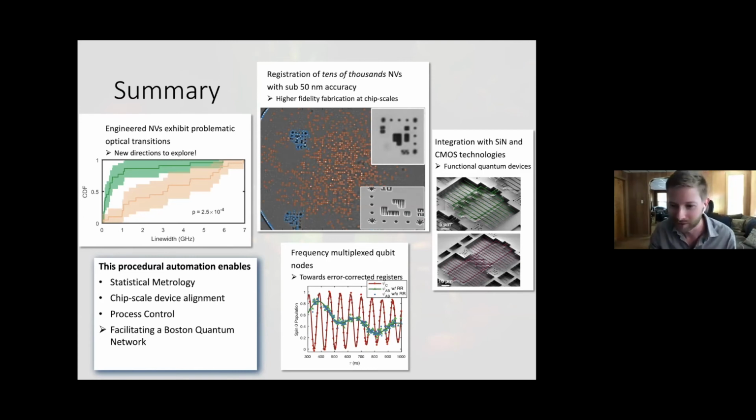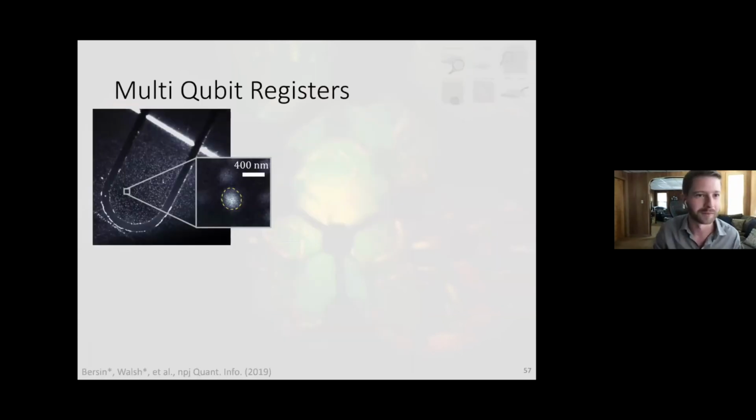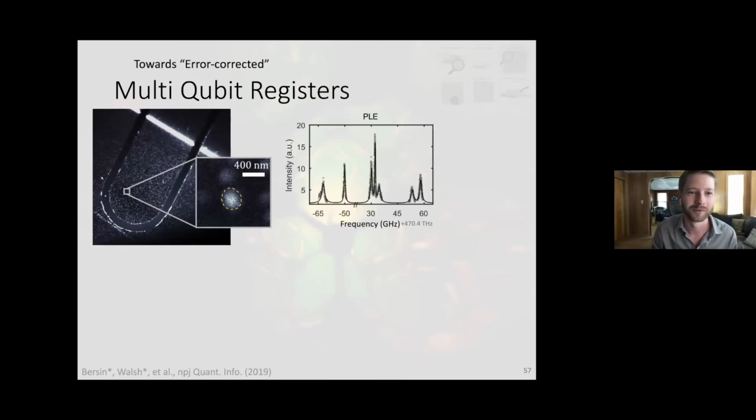And so let me just see if I have a backup slide here. Actually, right here is exactly what I'm talking about. In this particular node, we programmed the microscope to, instead of just going to find all of the sites there are, specifically look for a certain type of site where there are multiple emitters. The way the microscope was able to tell that is by looking at this PLE measurement, again, that excited state transition. Oh man, the slide is perfect for this explanation, where we have 3 different emitters here, without getting into too much detail.